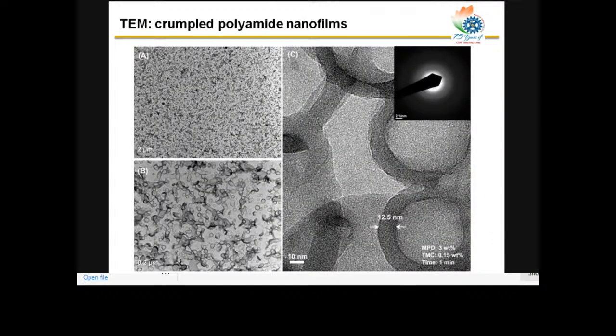This crumpled nanofilm structure, from the TEM image, you can see has a nodular structure. So the increasing surface area is quite visible here. And also in the cross-section image, you see they are bubble-like. So this hollow bubble structure will add interfacial area. That means the permeable area of the membrane. Next, please.